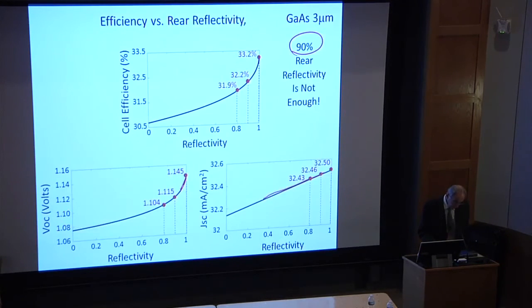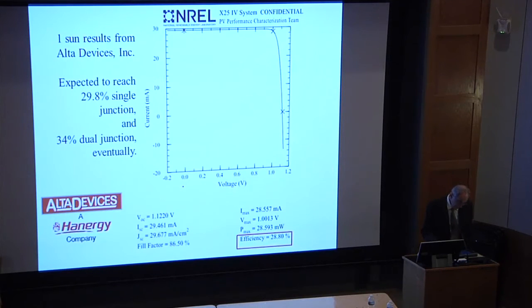And in fact, it's kind of interesting. I told them, test the luminescence efficiency. It's very easy to do that measurement. You just look at the light coming back at you. Test it, and only process the material that you've grown that has high luminescence efficiency. So you'll know in advance, is this going to be a record-breaking cell or not? So it saved them a huge amount of work, because they only processed the ones that were going to break the record. And so this is the record result.